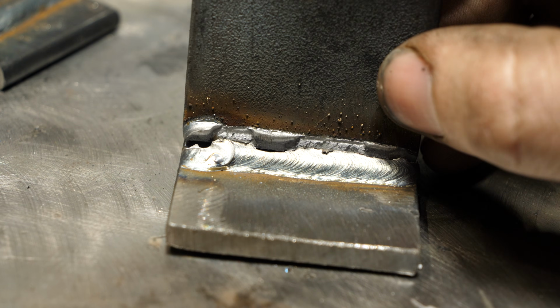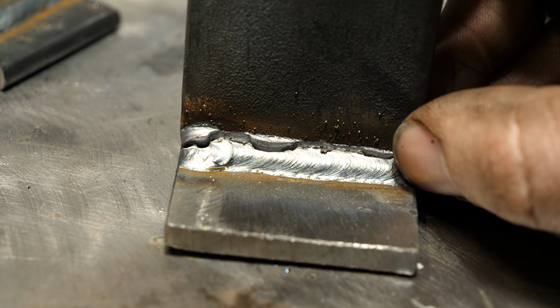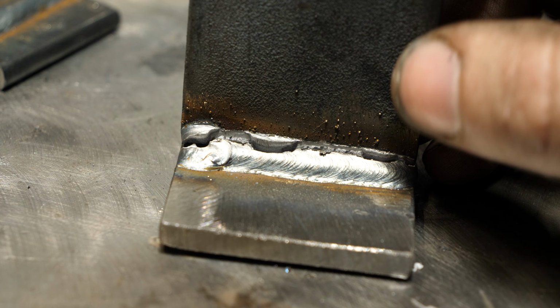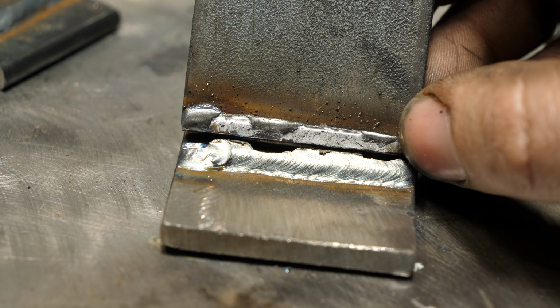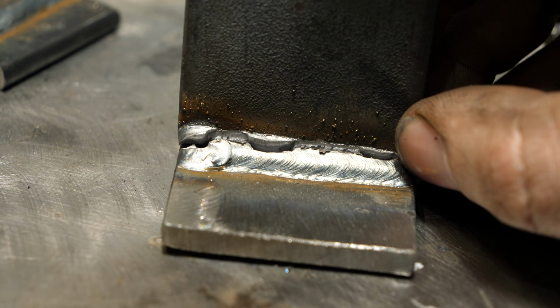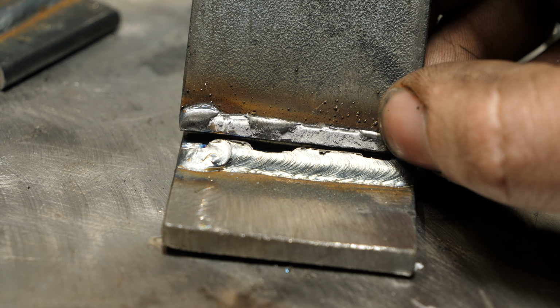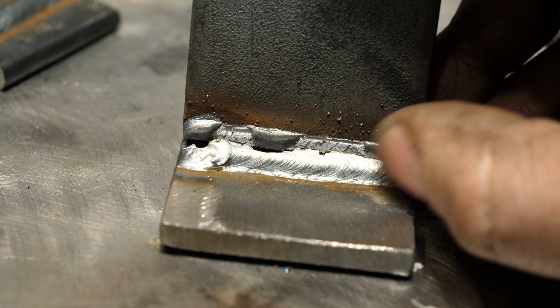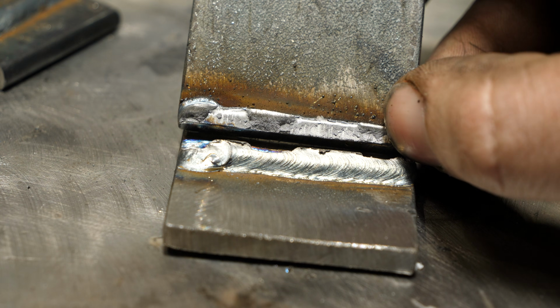All right, so this is a straight-in weld, and it failed at the lowest strength out of all of them, and the results are pretty apparent as to why. So the whole top of the weld didn't have much for fusion into the plate here, and essentially it just broke off.